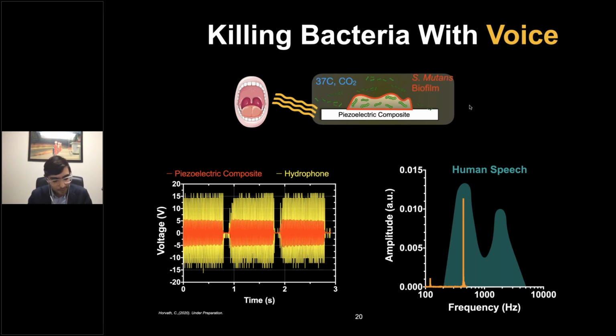Now, something we're also very excited about is that these piezoelectric materials can also get activated, the charge generation can also get activated by acoustics. A lot of the pickups, the microphones we use for electric guitars, basses, and even the ones we use for voice, use piezoelectric transducers. The acoustic signals you send are converted to electrical charges, and that's exactly what we're trying to do here. Use this acoustic wave as a means to stimulate the composite, and as you're stimulating, we generate the charge, and that charge can be used to prevent biofilm formation.